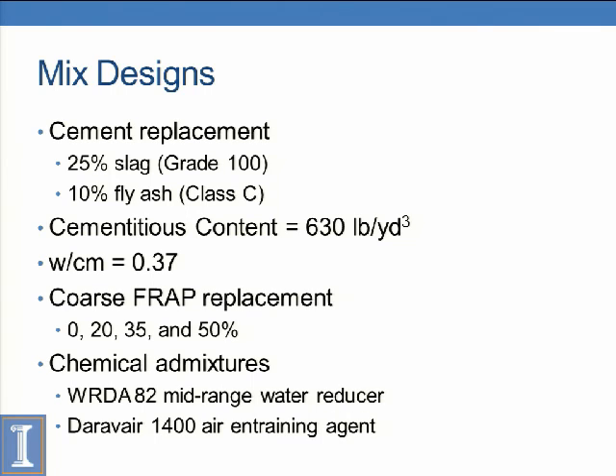Water to cement ratio was 0.37. Again, a little bit low compared to a normal pavement of say 0.4, 0.42. And then the real important thing, we looked at replacements of 20, 35, and 50% of just the coarse aggregate with FRAP. And then also we used some chemical admixtures to get good workability and air entrainment. There's just the mix design if anyone's interested.